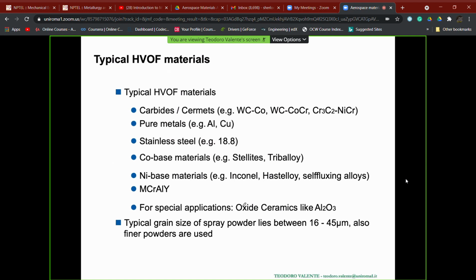So carbides, the tungsten carbide in a cobalt matrix, or in a cobalt chromium matrix, or chromium carbide in a nickel chromium matrix. Pure metals for corrosion protection, like aluminum, for example, copper, for the reasons I just mentioned to you before, or steel, again, for corrosion protection, or cobalt-based materials like stellites and tribaloy. They are metallic alloys, very hard on the surface. Nickel-based materials also, like Inconel alloy, can be made by HVOF, as well as MCrAlY, and some very few cases of ceramic like alumina, what I have told to you before.